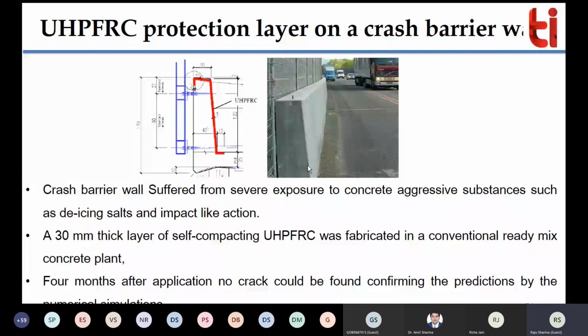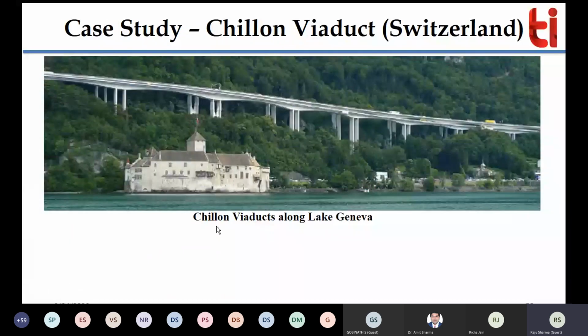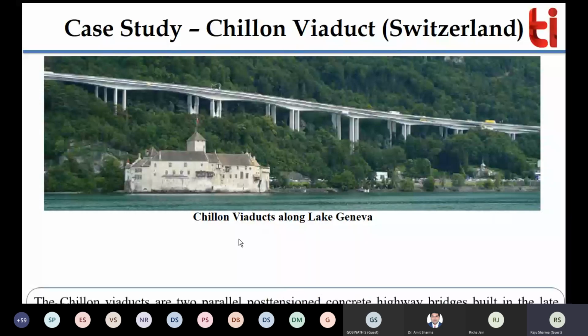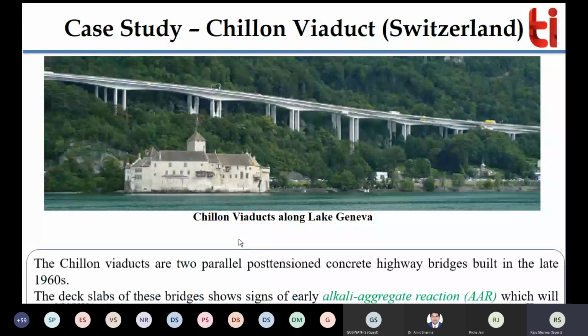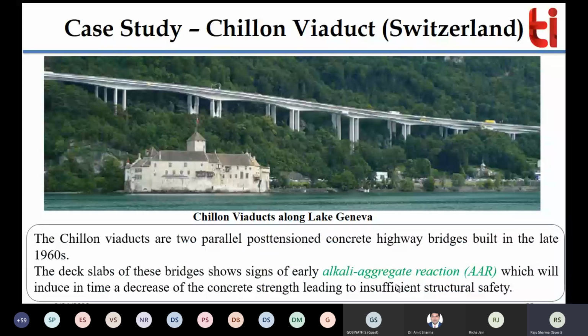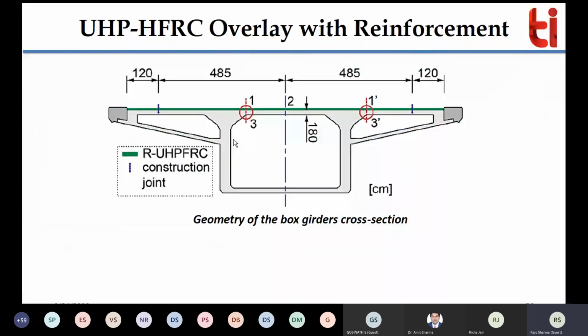And then they assessed the performance of this member after some months, and they found no cracks on the surface, right? And this is the case study of the Chillon Viaduct bridge in Switzerland, in which the top surface of the bridge was retrofitted using UHPFRC. It was built in 1960, and because of alkali aggregate reaction with the passage of time, the performance degraded, right? So in that case, they applied UHPFRC on the top surface along with the reinforcement, meaning a UHPFRC overlay with the reinforcement. You can see it over there, right?